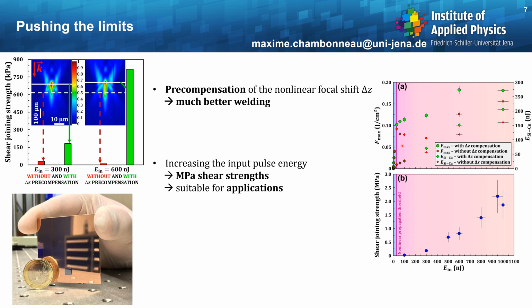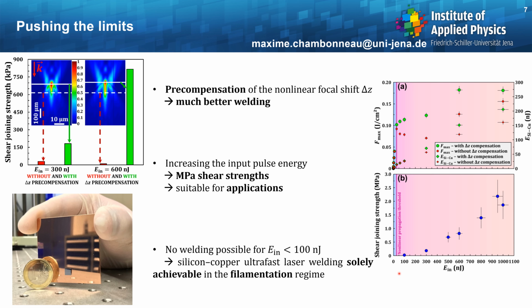Noteworthy, indicated in purple here, one can note that there is no welding possible for input pulse energies below 100 nanojoules, which means an important thing. It means that silicon and copper ultrafast laser welding is solely achievable in the filamentation regime.